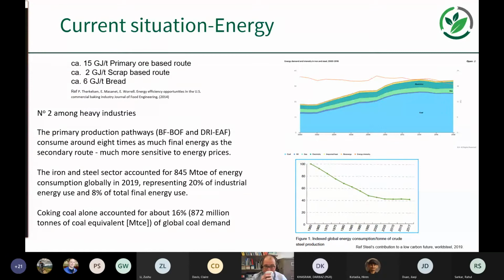So in terms of the energy, primary ore-based production is around 15 gigajoules per ton. So it represents far and away the most energy intensive of the processes. The scrap-based route is down at 2 gigajoules per ton, so significantly lower energy requirement there. And then I've just put a figure in to put some perspective on that. Per ton, bread takes around 6 gigajoules per ton. And of course, that's quite a highly processed material.